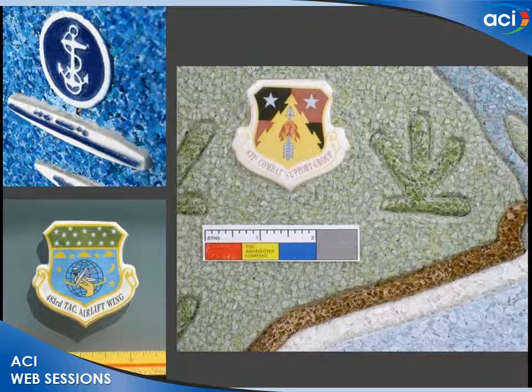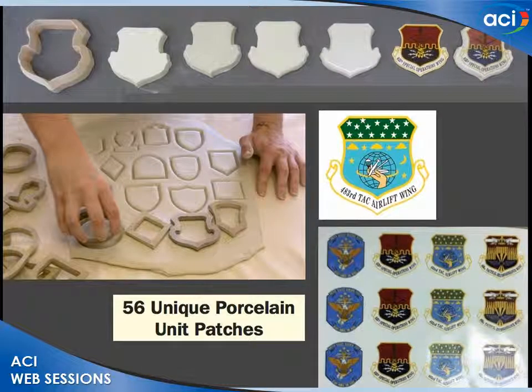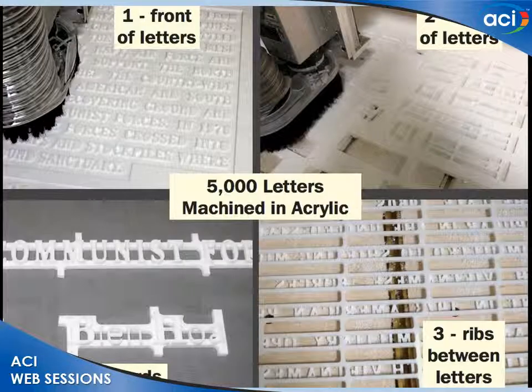And for that, we actually decided to use a porcelain rather than a more durable ceramic, and created a cutting template. It went through a seven-step process of drying and firing and preliminary glazing and final glazing. Fortunately, the digital printing process has come to the glaze industry, so we were able to get, these are actual glass glazes printed digitally based on our artwork.